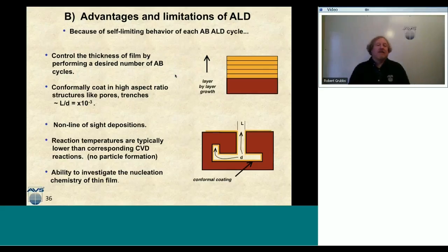Now, I've listed the advantages and limitations of ALD chemistry, and we'll just go through those. It's because of this self-limiting behavior that I described, for each of these ALD cycles, that really gives it its unique advantages. So the first advantage of this self-limiting behavior is that I can control the thickness of the film by performing the desired number of AB cycles. So if I needed 18 angstroms, I can give you 18 angstroms. If I need 320 angstroms, I can dial in 320 angstroms of this film.